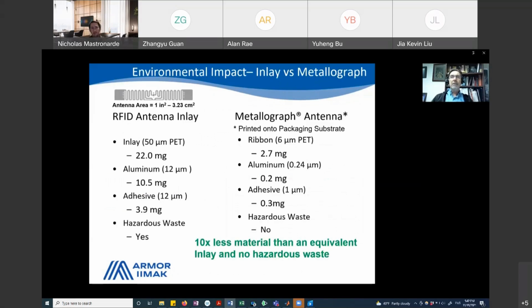The environmental impact of RFID tags, as I mentioned earlier, is an important factor as we all work to improve sustainability of the products we produce and the recyclability of the packaging materials they're shipped in. I've done a rough mass balance here to show that conductive thermal transfer printing direct to the substrate actually consumes about 10 times less materials overall than conventional RFID inlays and doesn't generate any hazardous waste. Starting with the metal consumed, there's actually 50 times less aluminum used than in an etched metal or foil inlay. This is a big sustainability advantage.